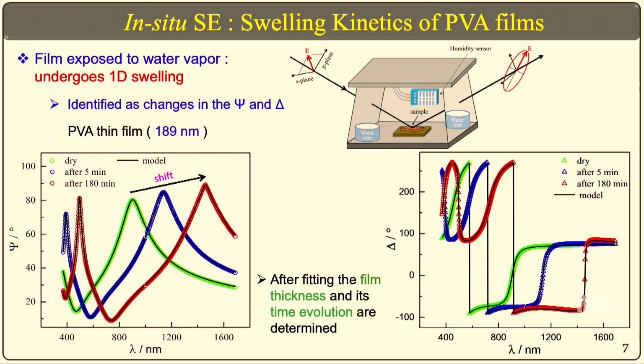That's an interesting thing, because generally in Chennai when we do the measurement the humidity itself is 40-50%. So the thickness is somewhere around, say suppose this is 189 nanometers, and when we do measurement at a very low humidity, we have a chamber, we pass through dry nitrogen. We can control the nitrogen flow to control the humidity. So when we go to 30%, 20%, 10%, we can see there's a decrease in thickness because now the absorbed water comes out actually.